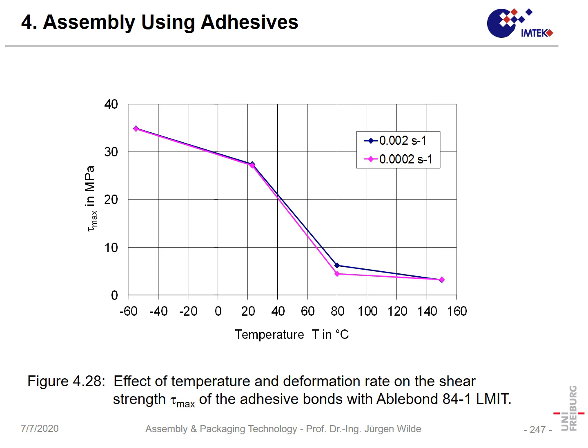When we look at the shear strengths for the other materials, I told you 10 megapascal of shear strength. In our case, we did an investigation of our own. Here we had something like 28 megapascal, and when it's colder, it's stronger. Going down again, it goes maybe from 30 megapascal to 3 megapascal. So again, the strength is decreased by a factor of 5 to 10 when we come from a low temperature range to a high temperature range. Anyway, most circuits also operate in that high temperature region, and the strength of these die attachments is still sufficient.